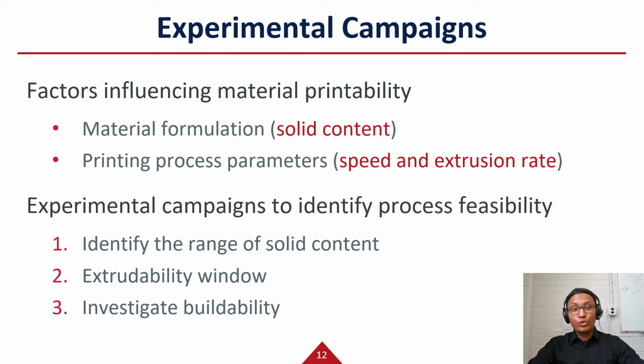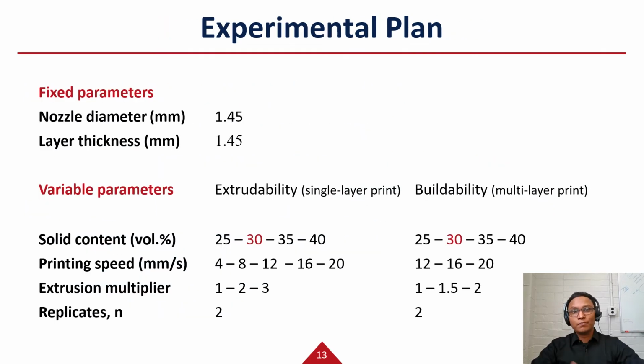In campaign 1, we identified the extrudability range of the material. Then, we updated those ranges to make sure that the material also has shape stability. Here is the plan for our full factorial design of experiments. We printed single layer parts for evaluating the extrudability and multi-layered parts for the buildability assessment. Across the experiments, we kept the nozzle diameter and the layer height constant.